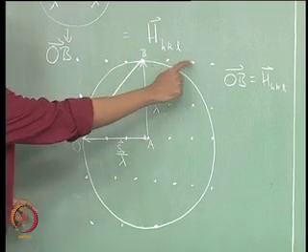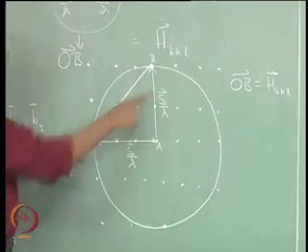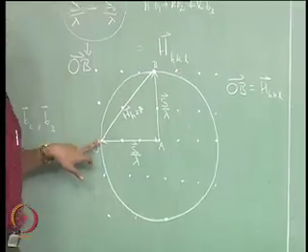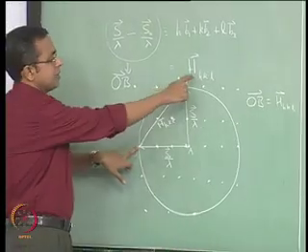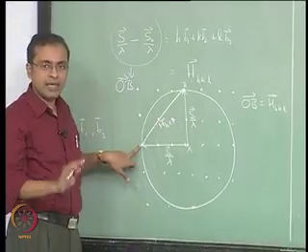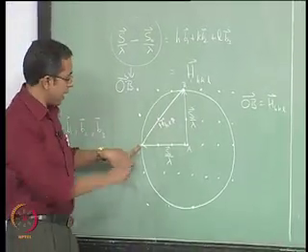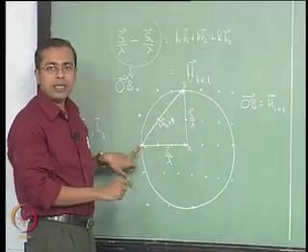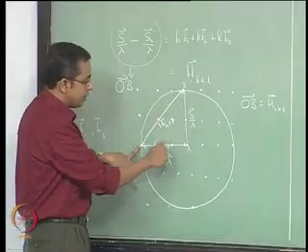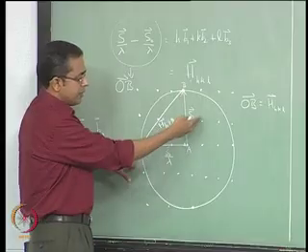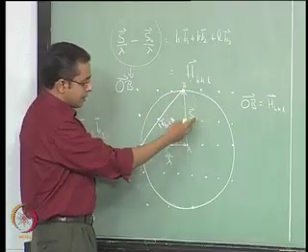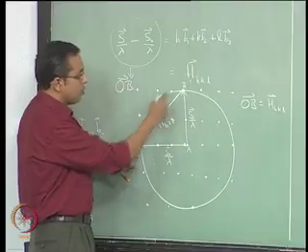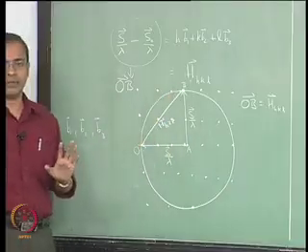If you connect the origin to a valid reciprocal lattice point, you have a valid reciprocal lattice vector which is designated by HKL. Anytime the circle also touches that point, then the difference between these two vectors, which defines the circle, is a valid reciprocal lattice vector.